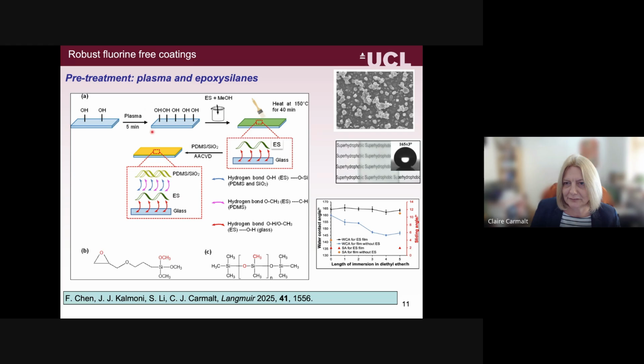So first of all, sometimes we do a mixture of both. So using air plasma, you can enhance the number of OH groups on your glass surface. We've also looked at adding an initial layer, just brushing it on and then heating at 150 for 40 minutes. And this was of this epoxy silane shown here, which again can just sort of act as a bit like a sort of glue. And then we did our AACVD.